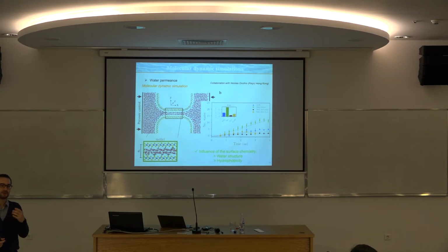And then he investigated the influence of the surface chemistry. So here this is the same d-spacing, just different functional groups. This was for, I think, a 20 angstrom channel height. And you see that the highest flux is actually obtained from methyl compared to ethanol, acetamide, and pristine MoS2. For pristine MoS2, there's a flux because it's 20 angstrom, that's why. If it's 10 angstrom non-functionalized, it will not pass.